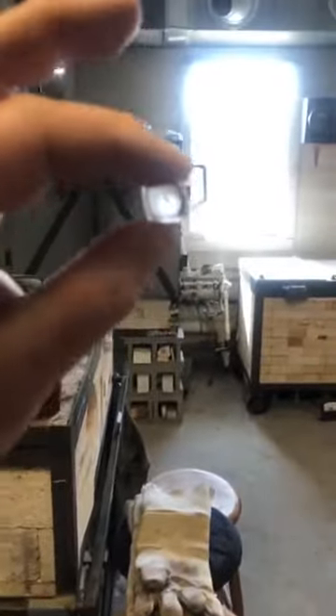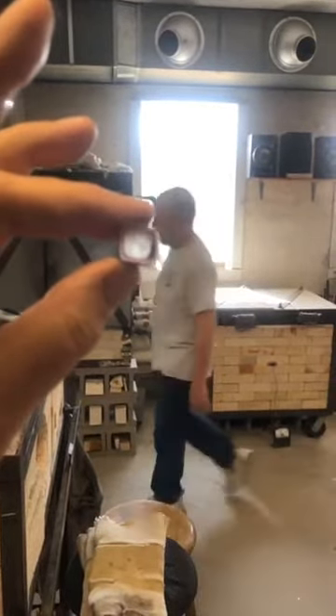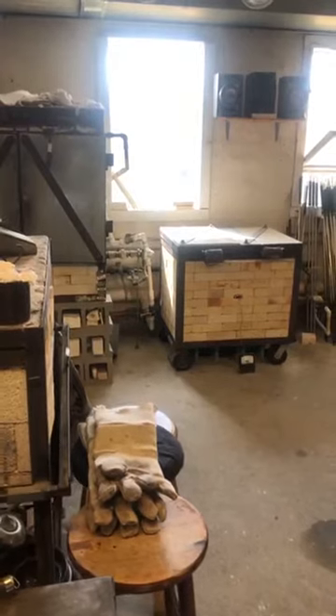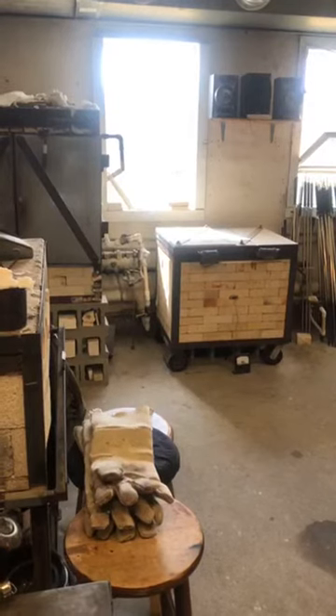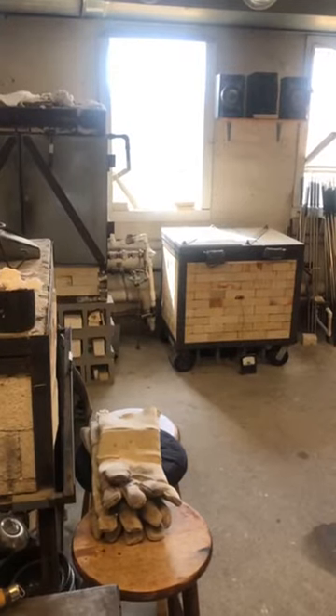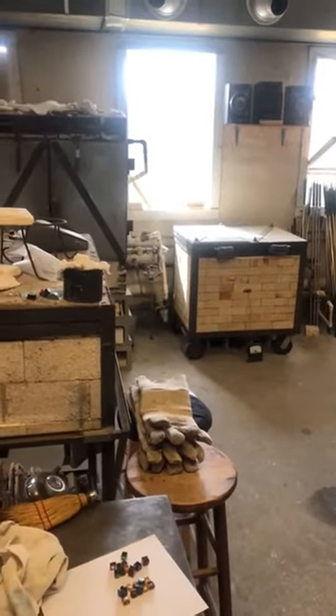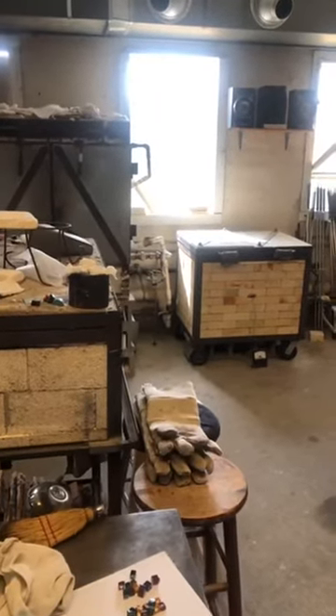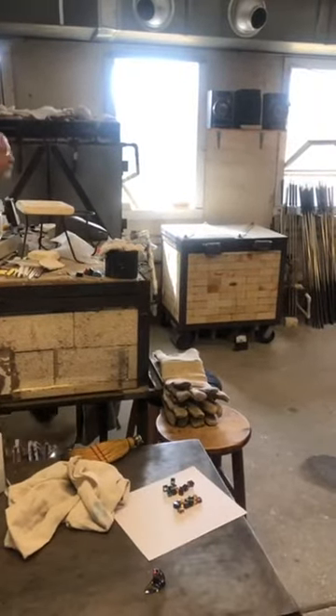is we take some colorful glass, and then we have to fill it with clear. We have a couple choices in that. We could basically make a cup, a color cup, and then stuff it with clear glass. Someone else could take multiple gathers and bring enough glass to fill it. But when a glass blower would like to work alone and do it by themselves, it's very easy to do what's called snorkeling the glass, creating a tube, an open tube, and the end of it is actually turned over a little bit so that when you put the pipe into the furnace, it makes full contact with the glass.